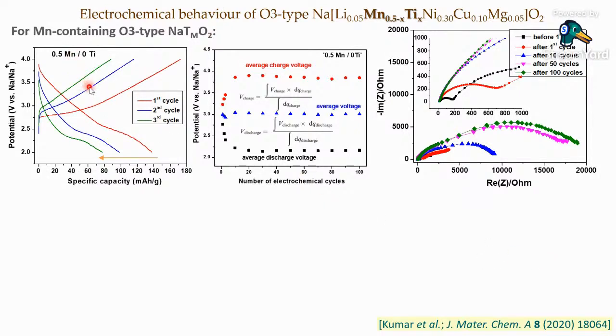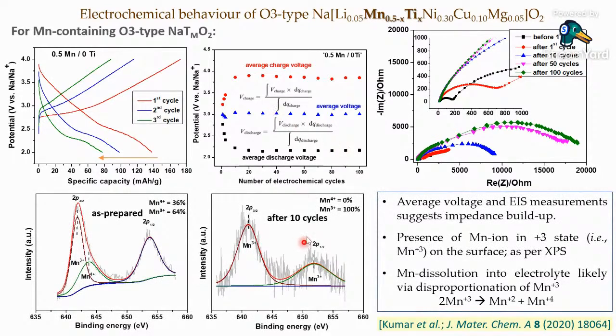The manganese containing material, with no titanium, showed a very poor performance. One can see decrease in capacity and increase in polarization very rapidly during cycling. And one could also find presence of manganese in +3 state at the surface, which is very bad because it can disproportionate into +2 and +4, with the +2 getting dissolved into the electrolyte. So it's a mess with so much manganese.